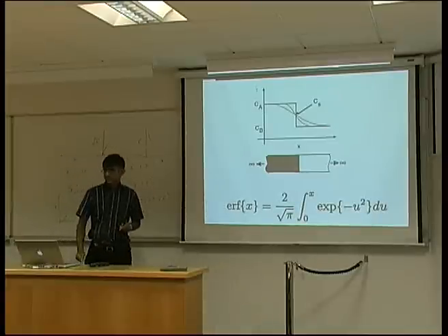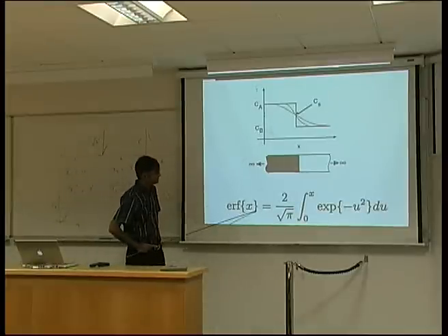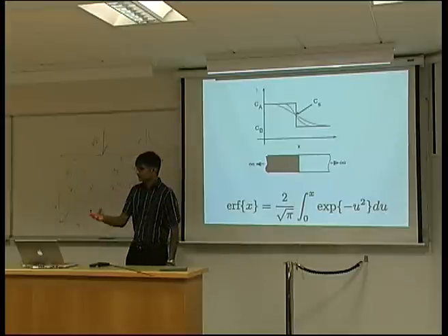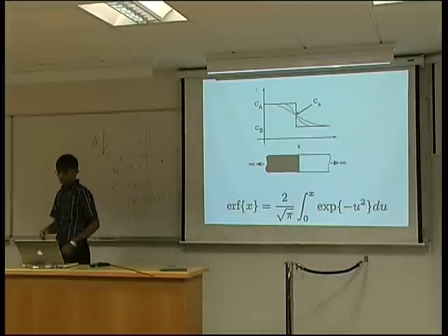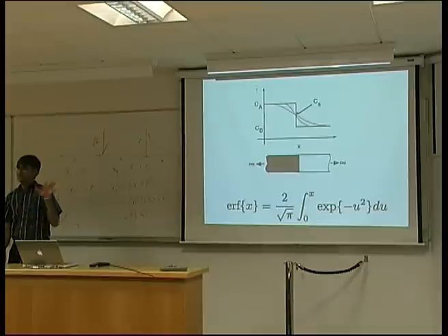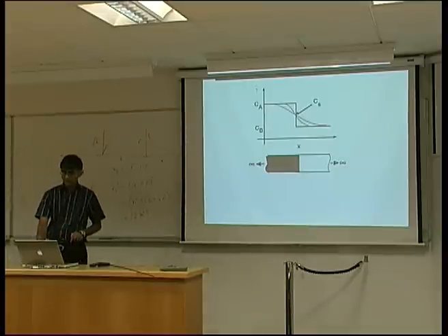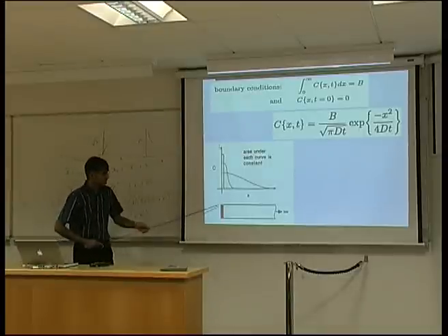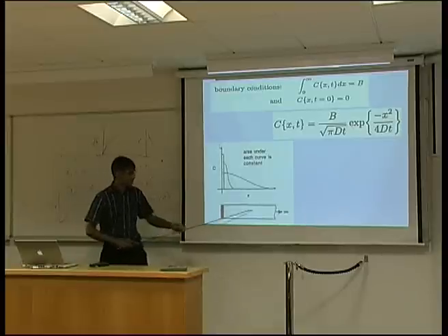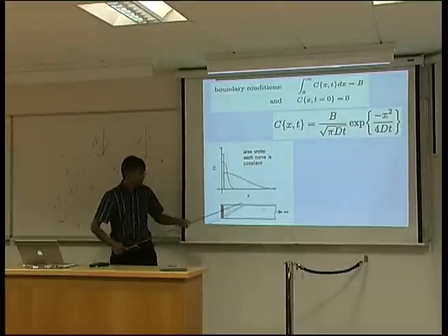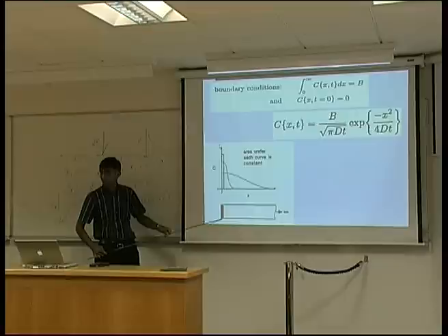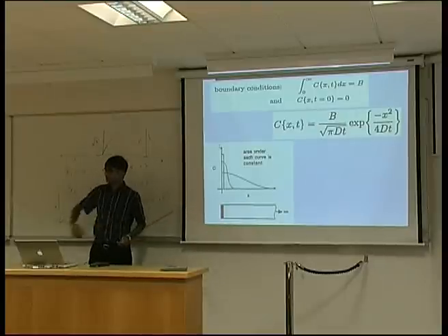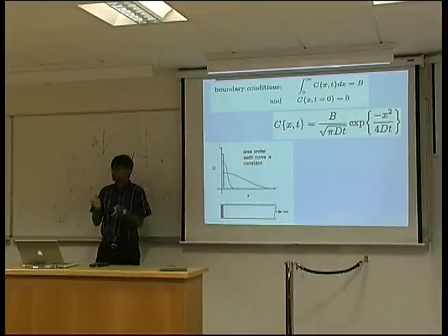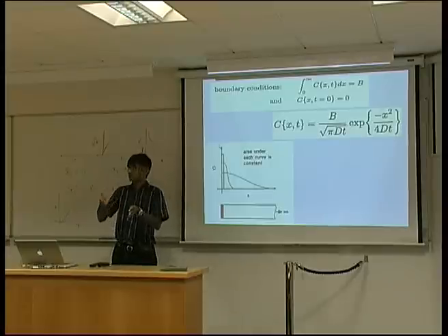And we describe this behavior in terms of what's known as an error function. And this looks very complicated, doesn't it? But actually, it is simply a derivation from the exponential solution we had. If I just remind you again, the exponential solution, we had a very thin layer plated onto a large bar. Supposing now I put another thin layer here, and another thin layer, and another thin layer, and carry on till infinity, then it's like I'm superimposing different exponential functions.